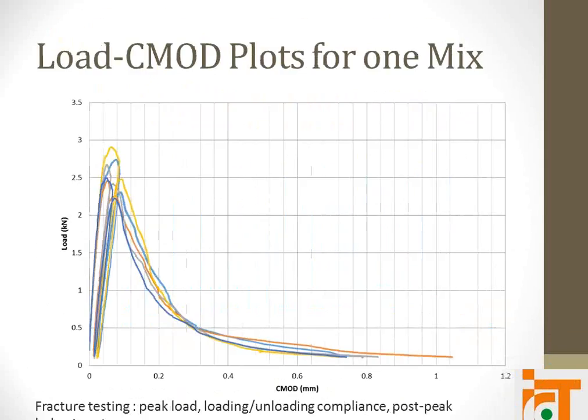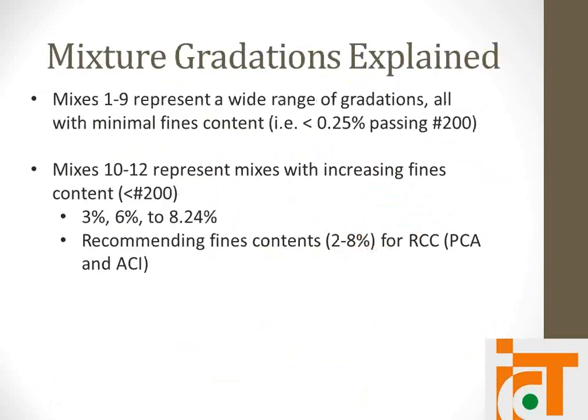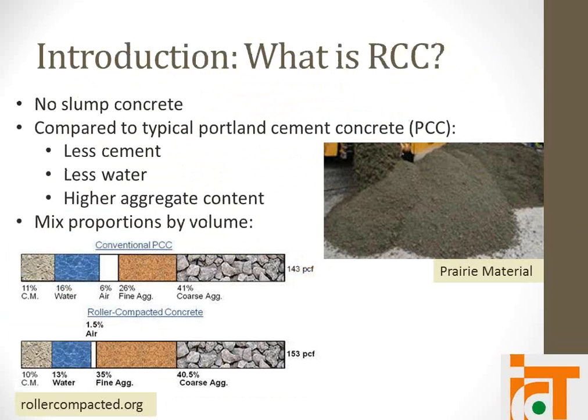Question for Jeff. On the first slide where you talked about the proportions, I wanted to ask what the difference in freeze-thaw characteristics of roller compacted concrete is versus conventional PCC, since the air contents are significantly different. That's another thing we are also looking at, especially with the low fines. We're not compacting the voids. First, we get air voids that are typical of concrete, and also have compaction voids, whereas we're not filling the structure as much as we expect.